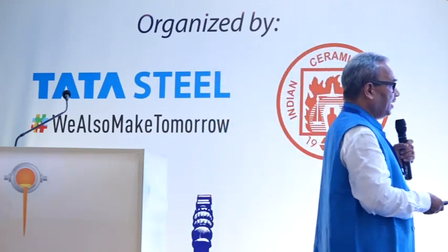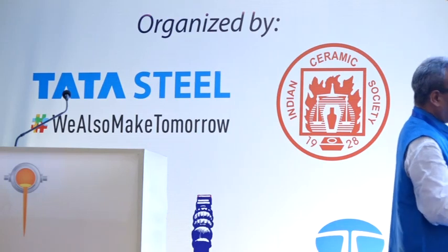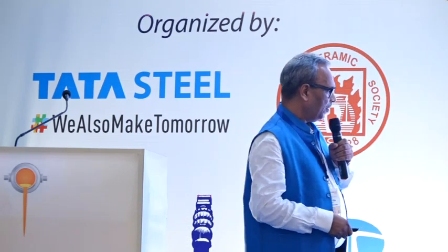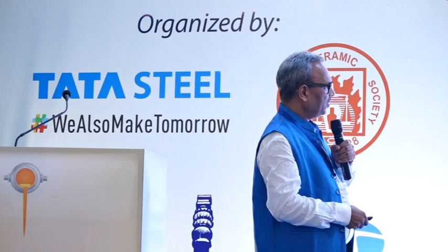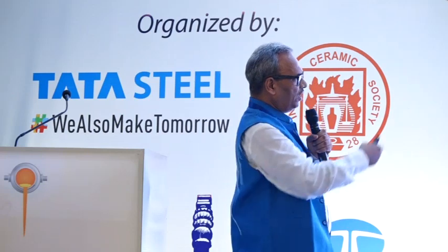And for steel slag, we can see BOF slag, EAF slag, and IF slag, basically induction furnace slag. And this is the production of the slag. And we can see the 15% change that has taken place over the years, in one year.